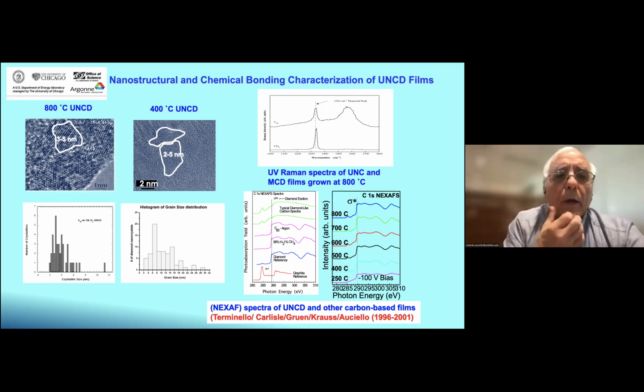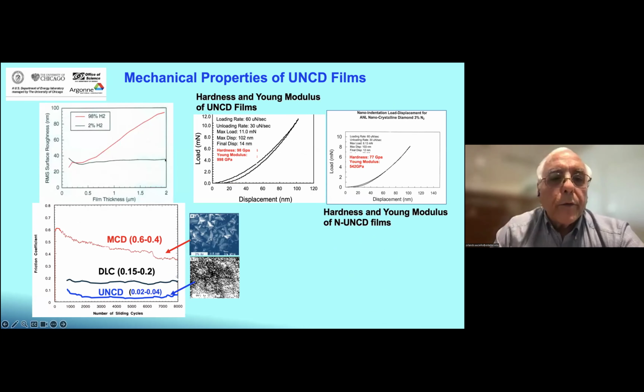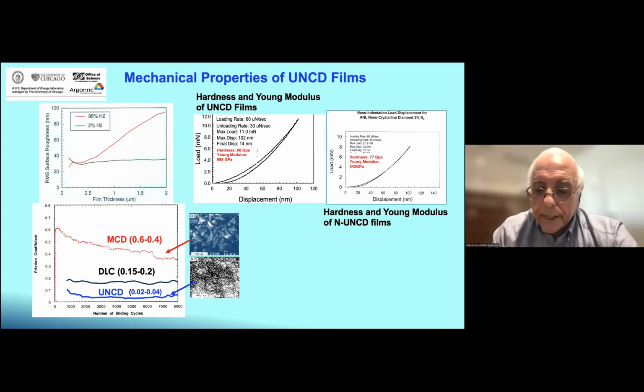So no matter how thick we grow the films, up to 2 microns in this example, the surface roughness is in the 2 to 5 nanometers, and our films exhibit the lowest coefficient of friction comparing with diamond-like carbon or microcrystalline diamond. And that is very important for some of the applications we have developed for products.